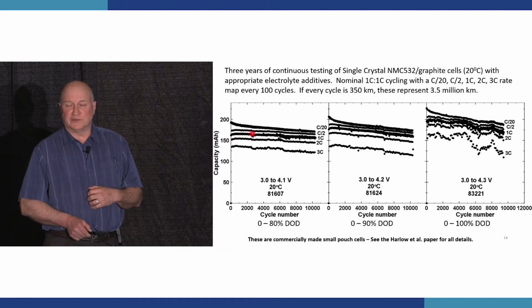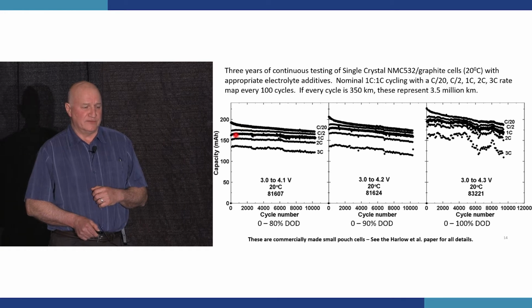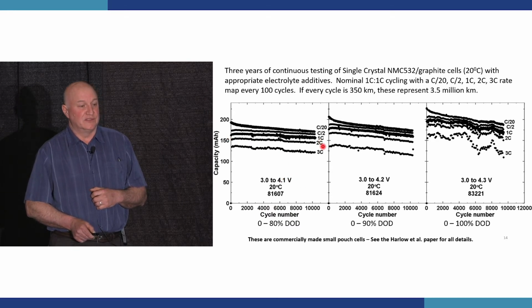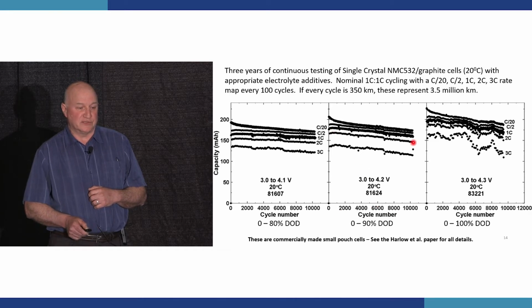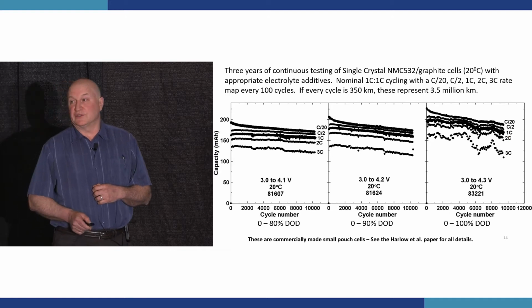So these are small lithium-ion pouch cells, and they have about 160 milliamp hours capacity at 1C when you're running them to a charge of 80% state of charge, or 4.1 volts. And you can see over these 10,000 cycles, with 3 years, there's virtually no degradation at all. If you charge to 4.2 volts, which represents 90% state of charge, again, there's very little degradation, but slightly more. And if you charge to 100% state of charge, or 4.3 volts, you can see things are still very, very good.